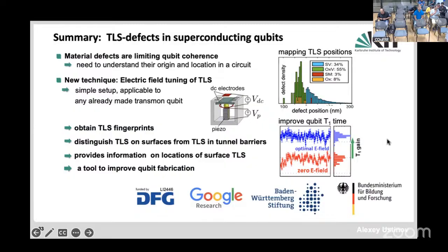Cobalt disilicide is also a superconductor, and cobalt disilicide does not form oxide. And it also has 1/f noise about 2 to 3 orders of magnitude smaller compared to aluminum. Yeah, I had a quick look at the paper which you sent this morning. It's interesting. I have not heard of this material. Of course, you mentioned that there is two-dimensional superconductivity in cobalt thin layers, and then cobalt silicide gets more three-dimensional with suppressed TC. Well, it's magnetic, so nobody knows really if one can make large circuits with that, but that's interesting to look at. Yeah, but that's an indication that if one makes a Josephson junction with cobalt disilicide, it will probably get rid of all these 60% extra TLS. Very interesting to check. I think it's a new material, new to me, and sounds interesting.